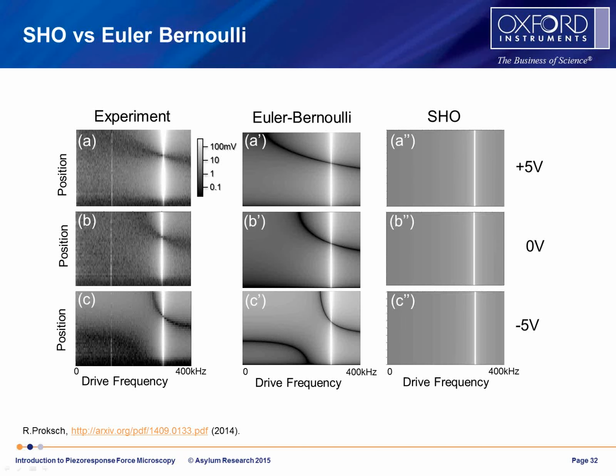So this next page just shows, and again I don't have a lot of time to go into this, these are experimental spectrograms made at a DC bias of plus 5 volts, 0, and minus 5 volts. And you can see there's changes in the shape of that first resonance. So this is 0 hertz. This is the base of the cantilever along this axis, and I've only measured in this case up to 400 kilohertz. The tip of the cantilever is up here, and you can see the evolution in that structure. Specifically, probably the easiest thing to look at is this antinode line, this node, this 0 amplitude line. It evolves as a function of that applied voltage in both cases.